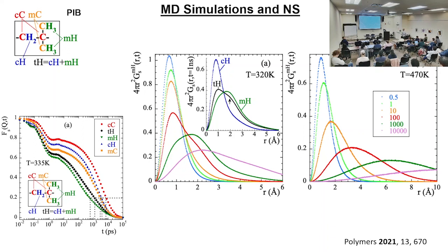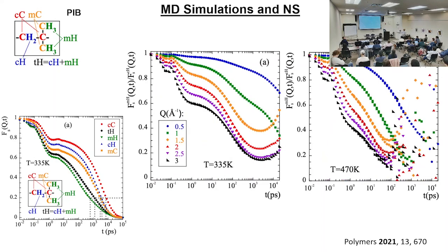If that is the case, then methyl rotation intermediate scattering function will simply be the product of the rotational part times the alpha relaxation, right? Now alpha relaxation is nothing but the chain, so you can substitute the overall methyl F(Q,t) by chain hydrogens and see actually if it makes sense.